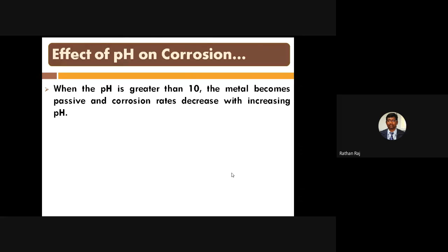After maybe 10, 15 or 20 years only, you are able to identify the carbonation, where calcium hydroxide is converted to calcium carbonate. This happens because of the loss of pH in the concrete. The steel bar used in reinforced cement concrete is protected from corrosion only because of this high pH environment, where steel becomes passive.